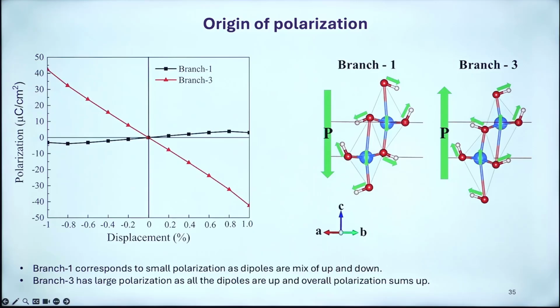So we saw that in branch 1 there is a compensation of each mode, a mix of up and down, so it is not very sizable. Whereas branch 3 has a large polarization, as all the dipoles are up, because we have to sum up all the dipoles. So branch 3 is the potential candidate when compared to branch 1. That's what we conclude from here.